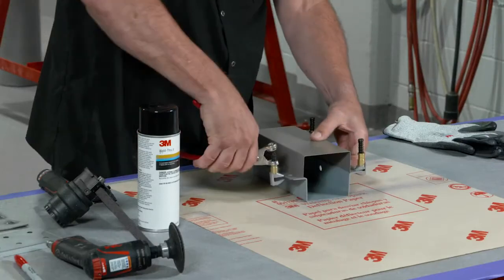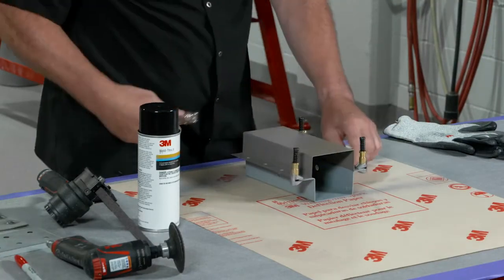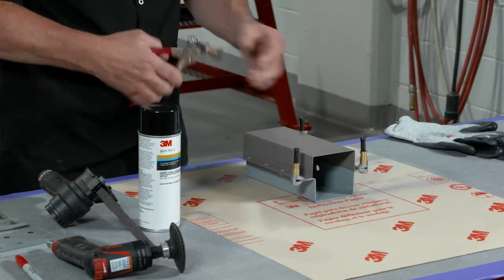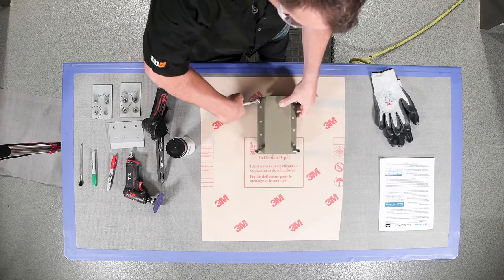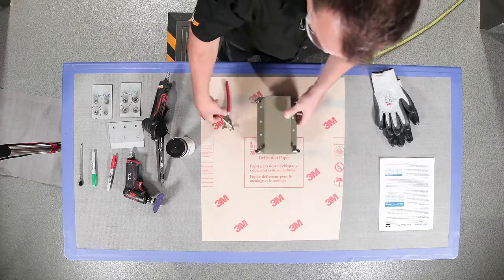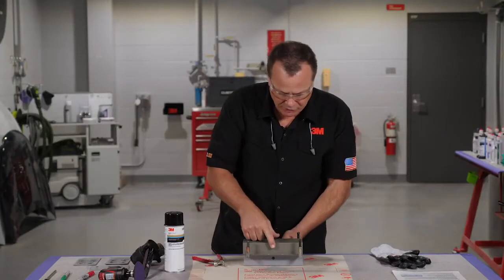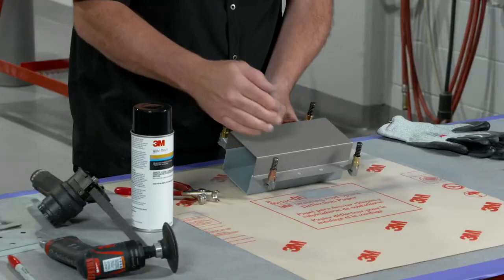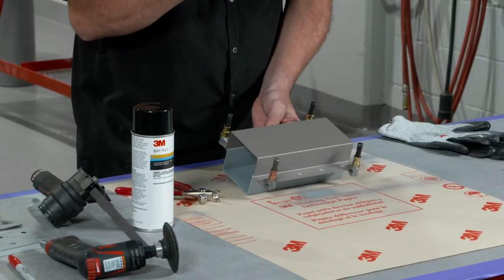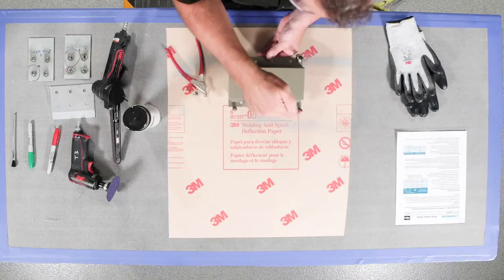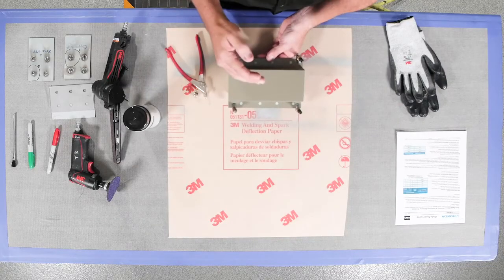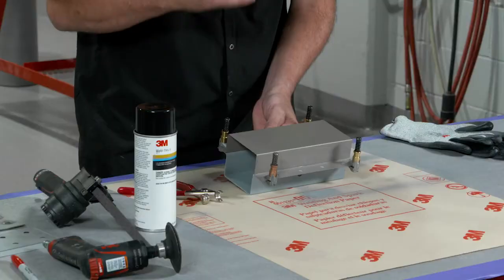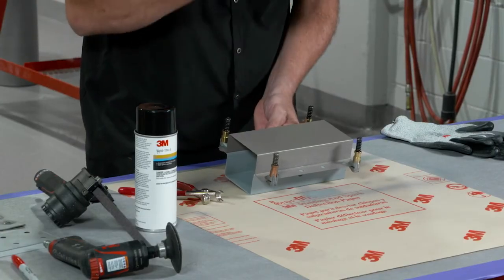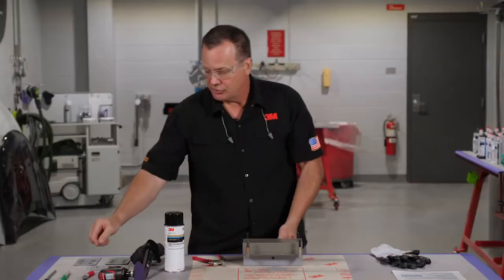So again, if we're working on a vehicle, I'm going to apply my clamps, line up all my gaps, and once I'm to that point, now I can see the Weld Thru primer exposed in the center of those plug weld holes. So if I try to weld over the top of that, we're going to get a very poor weld that's porous. And many OEMs, again, call out that it should be cleaned from the immediate weld zone.